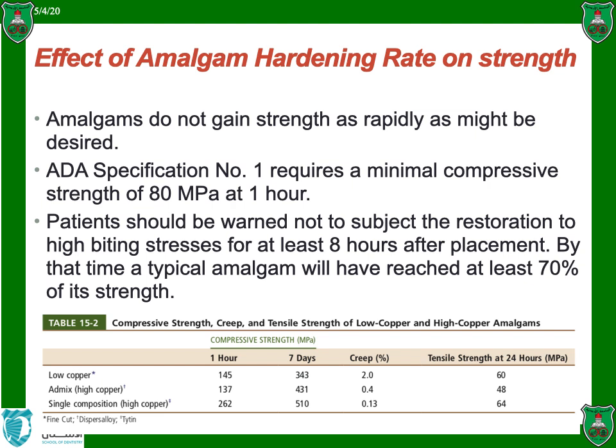So the patient should be warned not to subject the restoration to high biting stresses for at least 8 hours after placement. By that time, a typical amalgam will have reached at least 70% of its strength. And the ADA specification number 1 also requires a minimal compressive strength of 80 MPa at 1 hour.